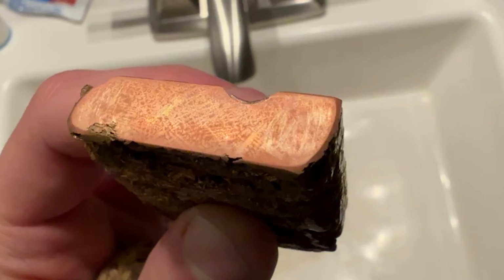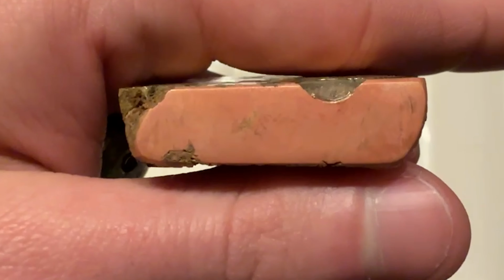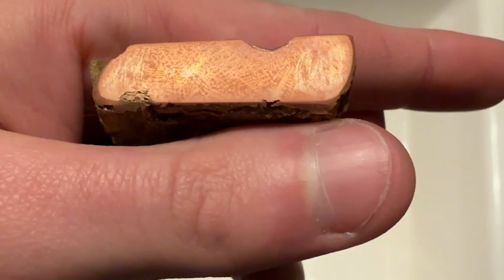The images up to this point were after a single etching pass, but I did a triple etch pass and the dendrite showed up much better. It's taken on this red hue, probably because so much of the zinc got etched away, leaving bare elemental copper. But you can see the dendritic pattern so much better on this ingot.